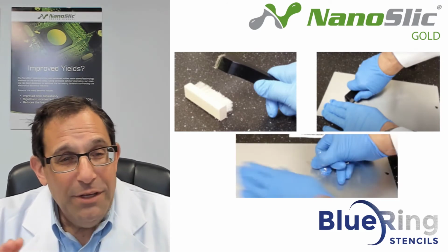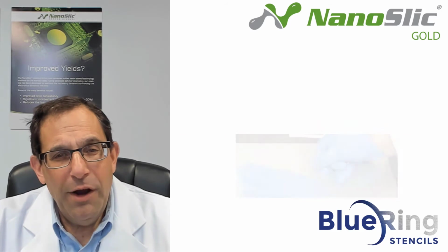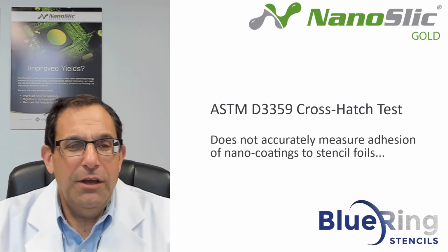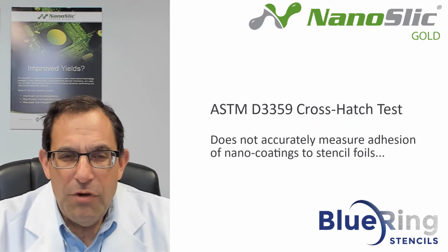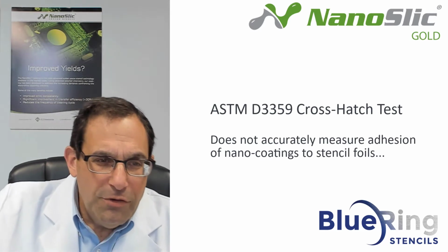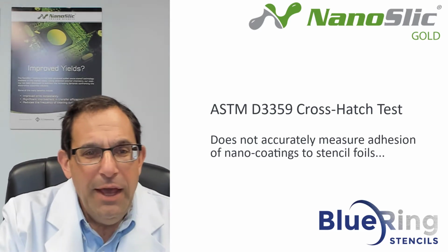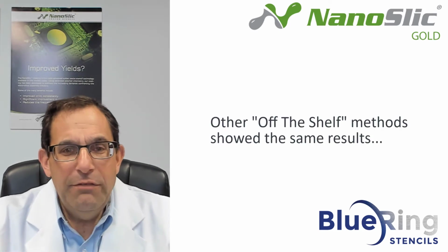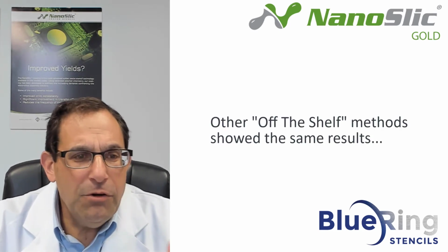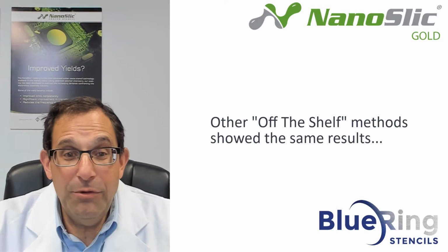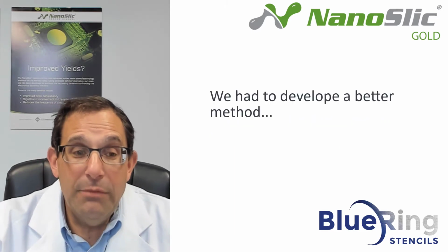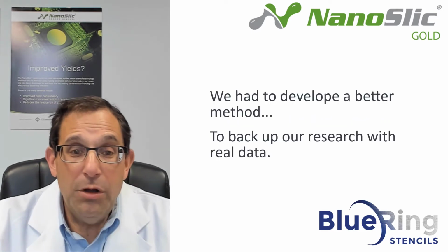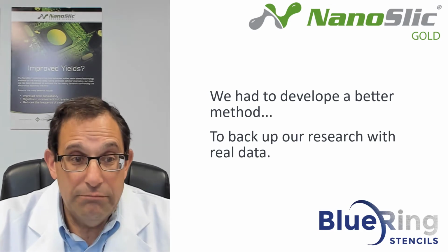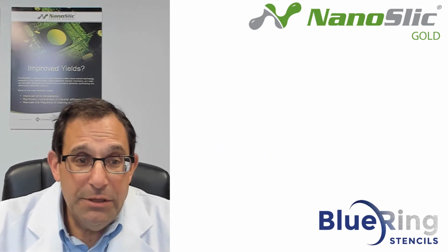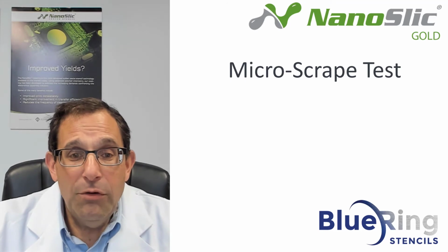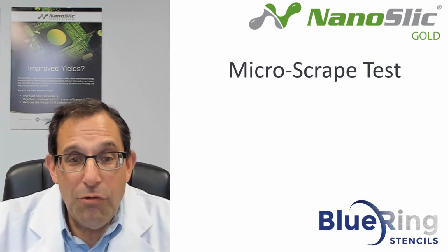But it doesn't accurately test the adhesion forces required to lift a stencil coating when it's subjected to the actual stress of stainless steel squeegees going back and forth, and the stencil and the coating flexing. We tried other off-the-shelf methods, but we had the same result. So we had to develop a better method. We wanted to back up all of our research with real data. The method we developed here, we call the micro-scrape test, or micro-scrape testing.